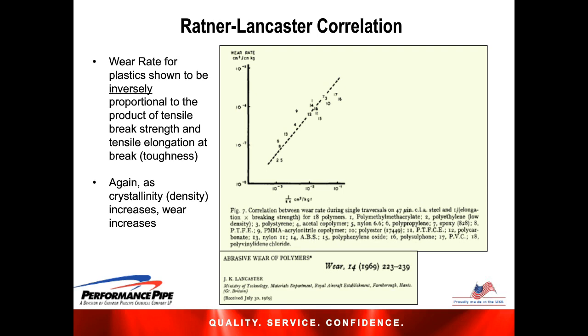Basically, the x-axis here, the product of the tensile strength at break and the elongation, is an indication of material toughness. Therefore, as toughness increases, this product increases. But note here that this axis is the reciprocal of that product, meaning that tougher materials are to the left side here, and they generally show less wear. Now, for polymers, many molecular factors will come into the picture, but other things being equal, generally lower density resins are tougher and therefore will exhibit lower wear per the results of this study as well.